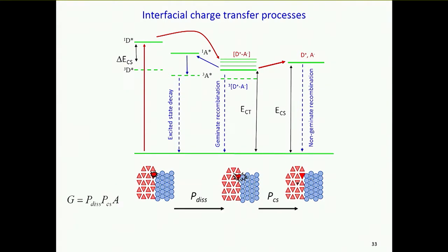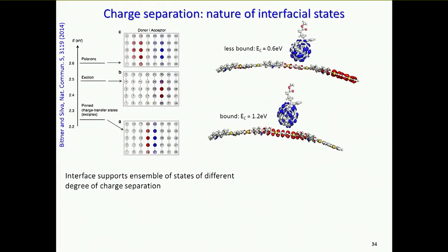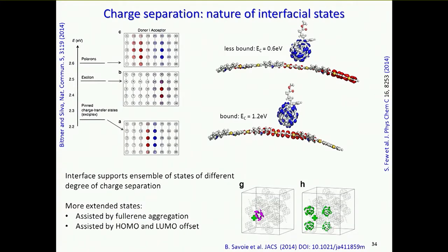The final thing relates to the idea that when you photoexcite your binary system, you have a polymer, you have a fullerene, or two components with an interface at which charge transfer can occur. We have information from literature, from spectroscopic and theoretical studies, that the evolution of the photoexcited excitonic state into a pair of separated charges, the efficiency of that process in a binary polymer-molecule system, tends to be enhanced whenever the small molecular phase, normally the fullerene phase, is able to crystallize. That was the point I wanted to make here.